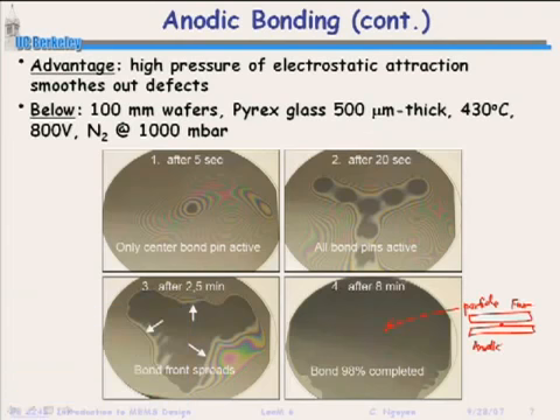So this is what happens with fusion bonding. But in anodic bonding, if I have this wafer here and I have that particle here, I've got a lot of attractive force between those two wafers. That attractive force is going to be strong enough that it's actually going to take the wafer above and bend it around that particle, such that you will get bonding everywhere except in a very small vicinity around that particle. So in other words, you may lose only one device, one die there, as opposed to losing a lot of die in the fusion bonding case. Anodic bonding is a very popular way to bond, in part because you can get higher yield off of this, even if you don't have the cleanest clean room in the world.